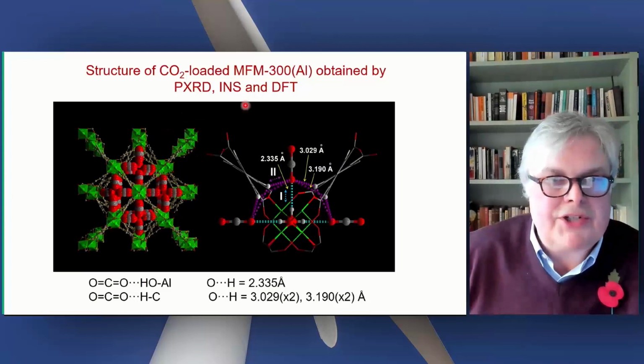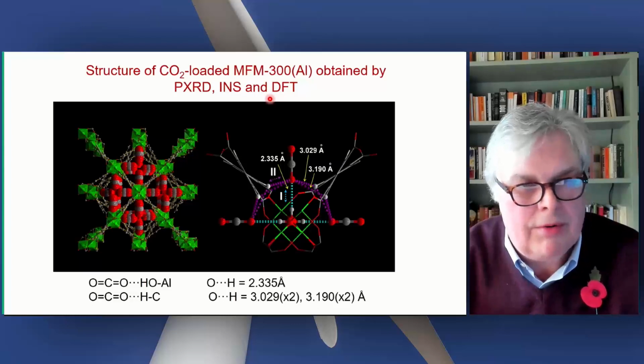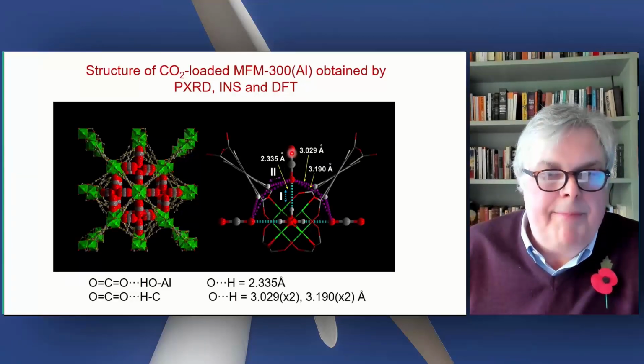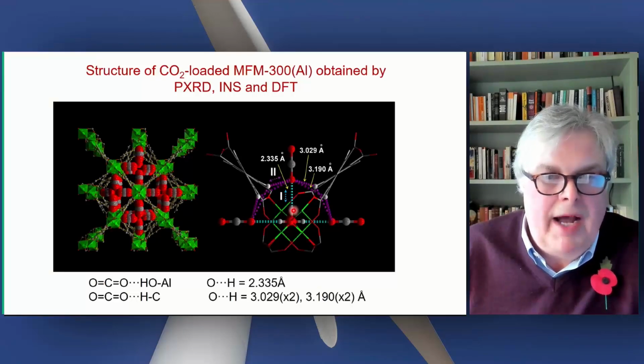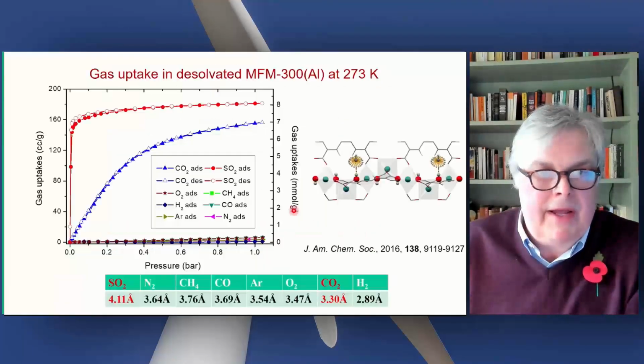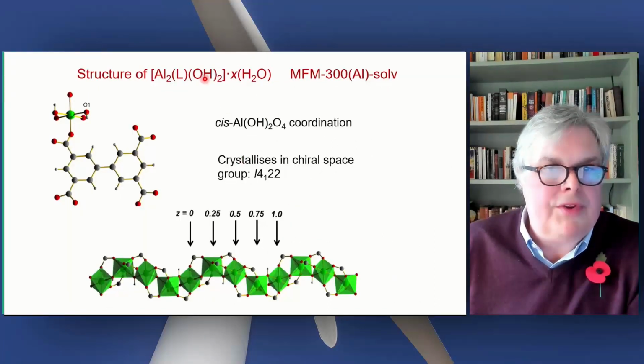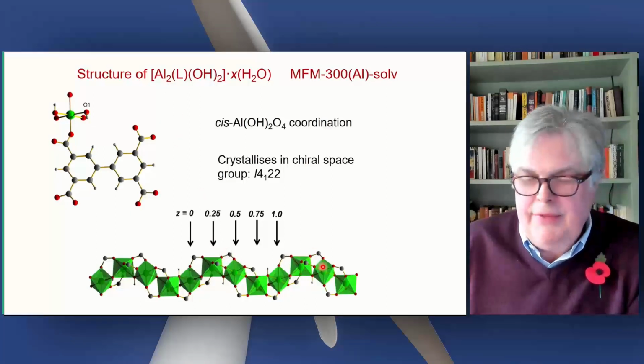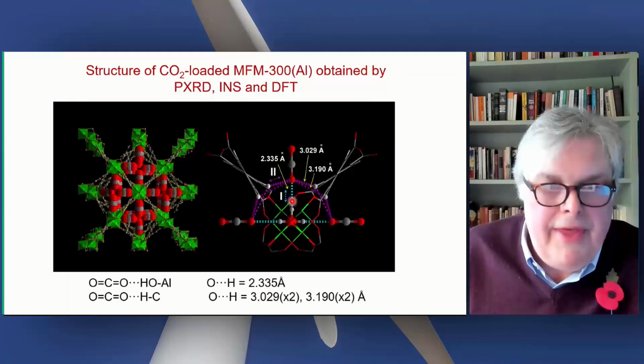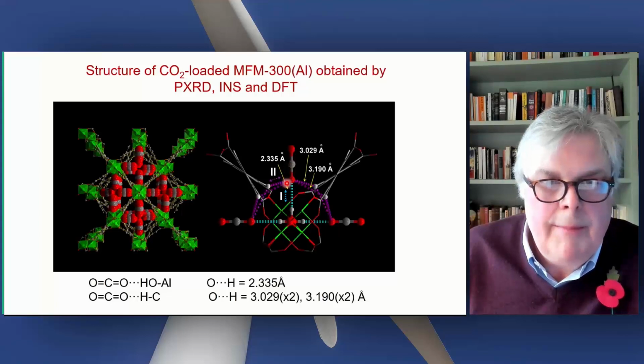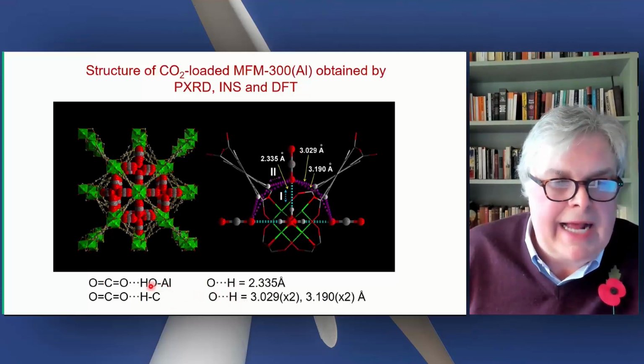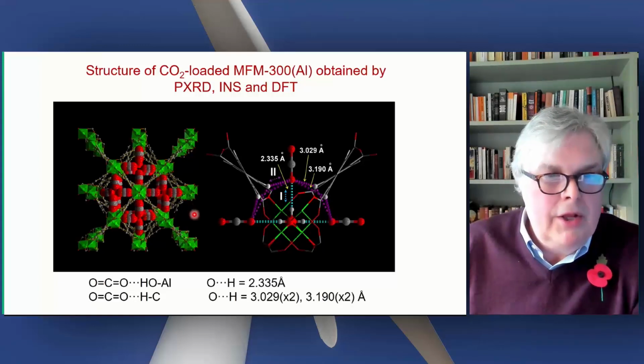The inelastic neutron scattering and DFT fit this very, very nicely. I won't go through all the details for obvious reasons, but the basic structure is, here is your aluminium hydroxy species. Remember, if I just go back, this has an aluminium with two hydroxys. There's a hydroxy group on the aluminium, and it's this hydroxy that also bridges the aluminium centers. So therefore, that is hydrogen bonding to your linear CO2, but very importantly, there are 4 CH interactions to this terminally bound CO2. So there is 1 interaction to an aluminium hydroxide and 4 further ones to CH groups from the aromatic rings. You can see this T shape.